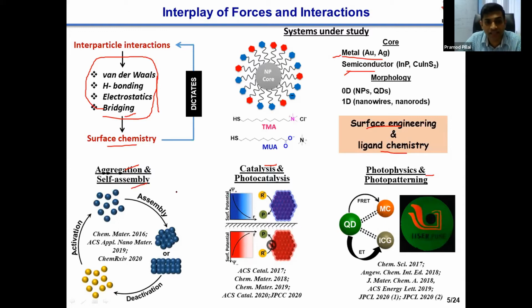In the area of self-assembly, or aggregation, we have seen that surface ligands can play a decisive role in dictating the thermodynamics of self-assembly. What I mean by thermodynamics is that these surface ligands decide whether a nanoparticle will form a self-assembled structure under an equilibrium condition or under a non-equilibrium condition. So this is the power of surface ligands in self-assembly. Similarly, in the area of photophysics, we were able to fine-tune various photophysical processes like Förster resonance energy transfer and electron transfer processes in quantum dots, and such fine-tuning of interparticle interactions helped us to create highly luminescent multicolor photo patterns, as shown in this particular figure.